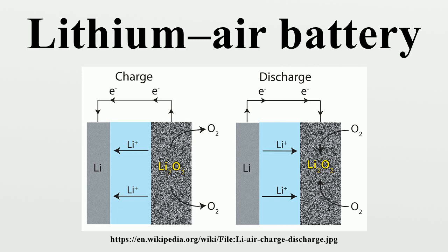Li+ + e- + O2 + * → LiO2*; LiO2* + Li+ + e- → Li2O2*, where * denotes a surface site on Li2O2 where growth proceeds, which is essentially a neutral Li vacancy in the Li2O2 surface. Lithium oxides are insoluble in aprotic electrolytes, which leads to cathode clogging.